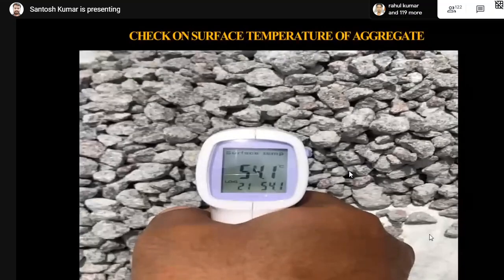When I went to the batching plant, as requested by the contractor, I saw the aggregate temperature; it was burning hot. Ramagundam is one of the highest temperature areas in the Telangana region, especially in peak summer. The temperature of the aggregate was 54.1 degrees. So with that aggregate, you directly put it in the batching plant and expect a slump of 170, impossible. The surface condition of the aggregate should be monitored frequently.